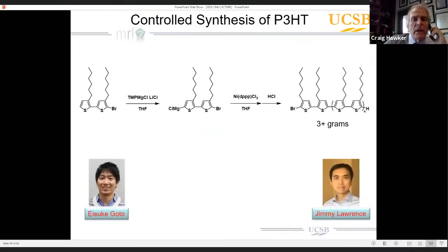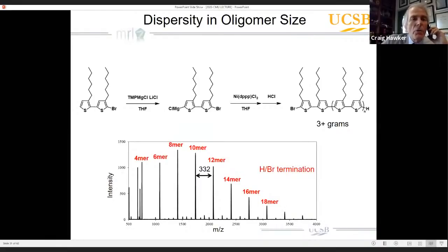And again, this is some work that Jimmy and a visiting researcher from Japan, Eisuke, took on. Again, controlled polymerization is our starting point. In this case, the controlled synthesis of P3HT. We're going to use a dimer strategy. The crude mixture of this has hexamers in there, octamers, decamers, dodecamers. You can see it's a fairly broad distribution of oligomers, even though the dispersity of the crude polymer is about